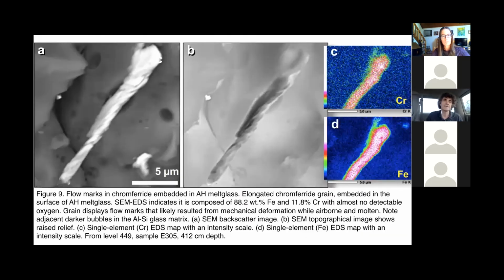When I first looked at this image, it reminded me of Pele's hair. Pele's hair is a kind of volcanic material, wind blown, making these long features in Hawaii. But this is not Pele's hair. This is much smaller, right? If you measure the composition, it's 88% iron and 12% chromium, and there's no oxygen. So it's very reduced, right? No oxygen found in this grain. So this is very spectacular, and perhaps the surface was made because of airborne formation.